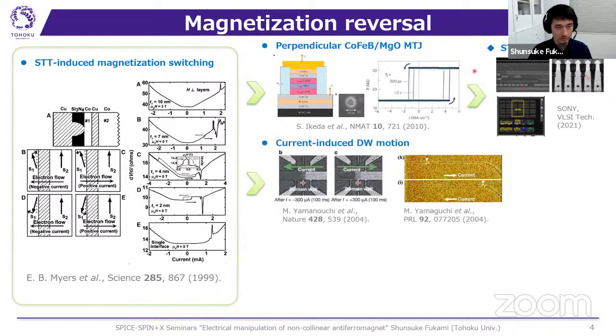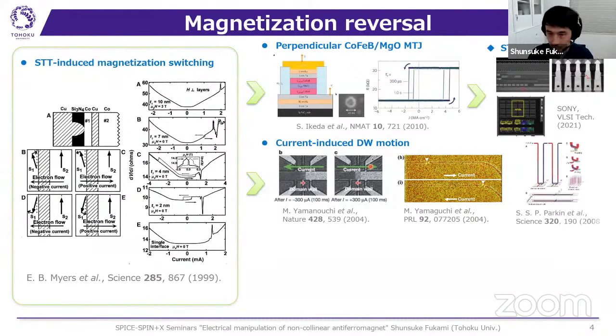And also, this is different from the spin transfer torque induced magnetization switching, but the spin transfer torque can also drive the domain walls. This is a famous work by Tohoku team and Teruo Ono's team, and Stuart Parkin also did wonderful work regarding current induced domain wall motion, and the racetrack memory was proposed that can, in principle, realize very large capacity storage memories.